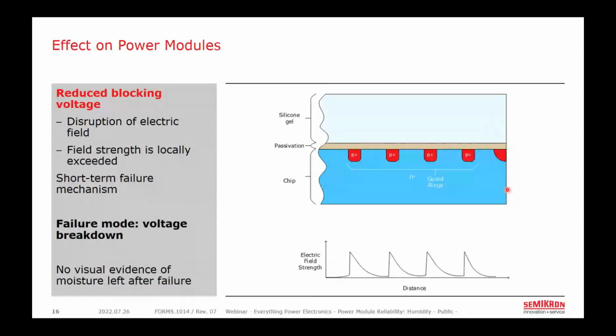And so in the case of an IGBT, the top of this chip is at emitter potential, and the bottom of this chip way down here is at the collector potential. So the chip thickness is determining the blocking voltage of this device when it's in the off state. And normally when we get towards the edge of the chip, we have this termination structure here consisting of field plates, guard rings, and some passivation, which divides the electric field into these nice, evenly distributed regions to prevent the chip from breaking down when it's in its blocking state.